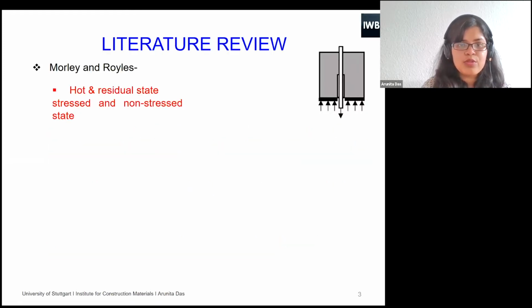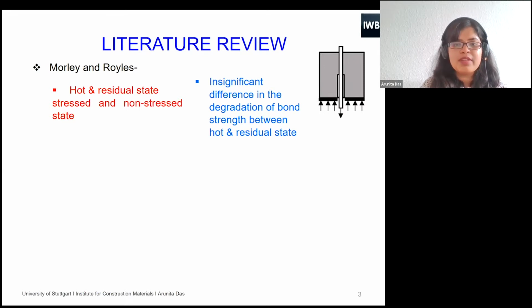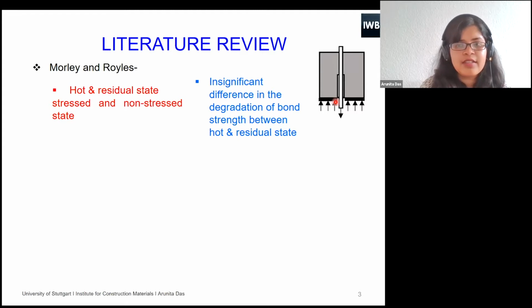So if we go quickly through the literature, what previous researchers have done: Morley and Royles considered hot and residual states in case of stressed and non-stressed states. And they concluded that there is an insignificant difference in the degradation of bond between hot and residual states. They considered pull-out specimens, as you can see. So it's basically a confined test.